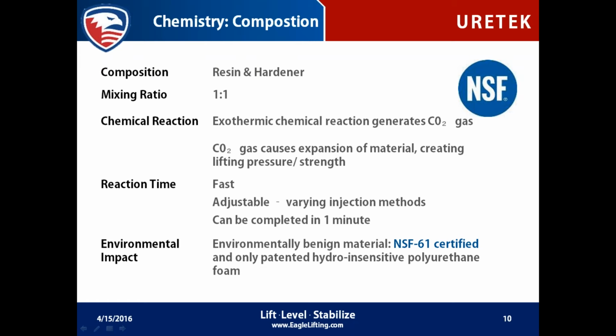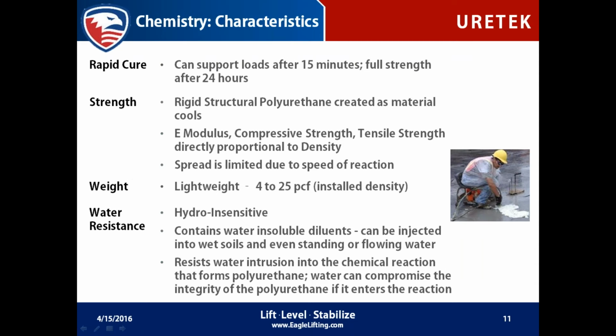We actually have our NSF 61, which means the polymers can be injected on, near, in, or around potable water. I don't recommend drinking the stuff. However, it is perfectly safe for you once the reaction's occurred. It has a rapid cure that can support loads after 15 minutes. As a matter of fact, it reaches about 90% of its total yield compressive strength within those first 15 minutes. After about 24 hours, it's ready for a full load and it's reached full strength.